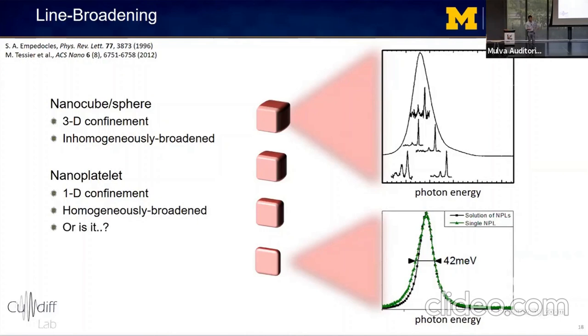We were a bit skeptical of this common assumption, however, since, as you can see in the top right, the single particle line shapes can vary really dramatically even within an ensemble. So when you perform these single nanocrystal measurements, you don't know whether you're looking at a representative nanocrystal or just an outlier. So to truly claim homogeneous or inhomogeneous broadening of your ensemble, you really need to perform measurements of an ensemble.